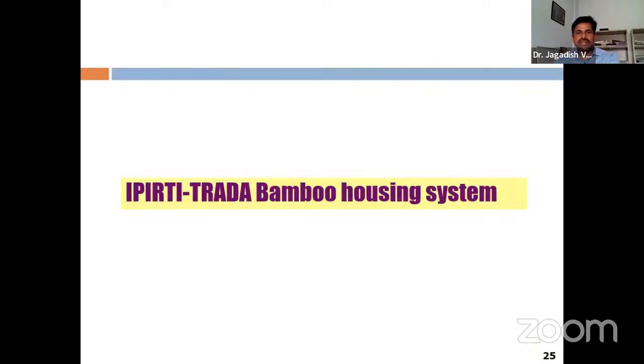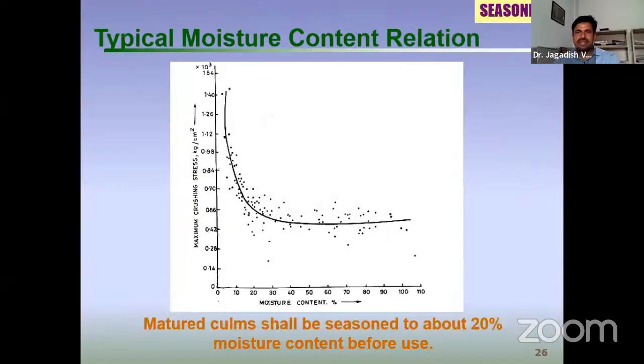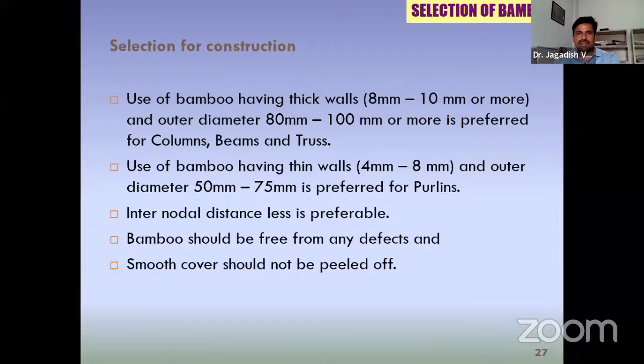Coming to one of the housing systems developed by IPIRTI, where I have worked previously. I will explain this housing system, wherein freshly cut bamboo contains a lot of moisture, almost 60 to 70%. When you see moisture content versus crushing stress, that means all the strength, the more the moisture, the less the strength. So you have to season the bamboo to a moisture content less than 20%, wherein you get the required strength for the bamboo. So the main thing is, when you freshly cut the bamboo, make sure you season it to 20% and then use it for your construction purpose.